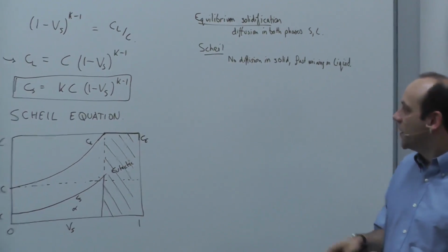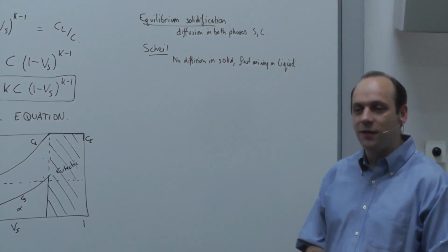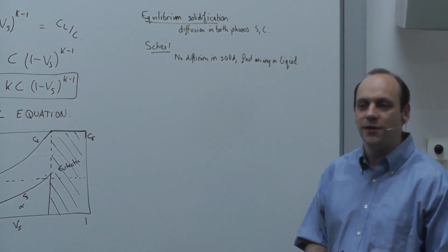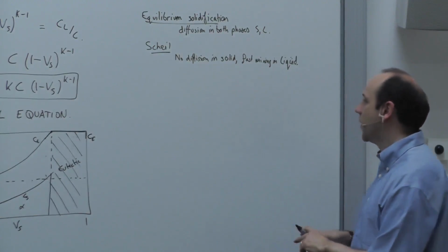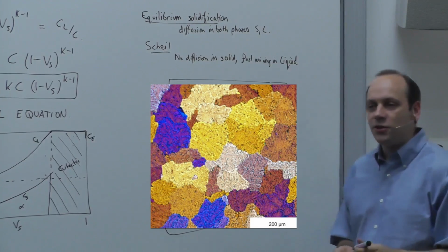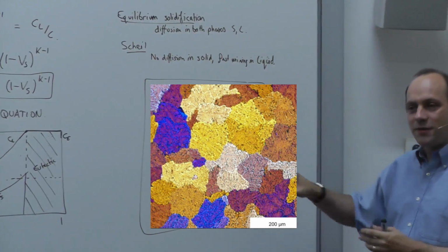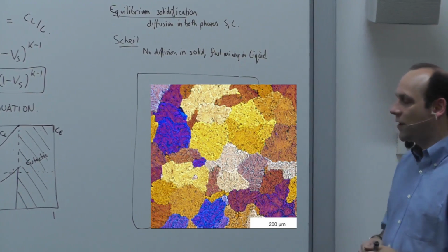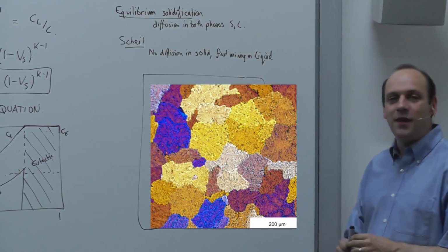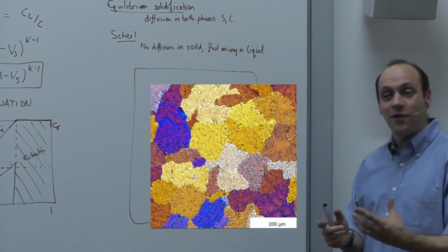solid that forms. So by now, many of you will have done a lab where you've seen solidification happen. You've seen solidification where the crystals grow as dendrites, probably from the walls of the container that act as the nucleation sites. So what this looks like, we'll show in a picture here, which shows the solidification of an aluminium alloy. You can anodize aluminium alloys to give you pretty colors and interference contrast when you look at it in an optical microscope. And you see there you've got a variation in the coloration of the solidified crystals, of the dendrites.